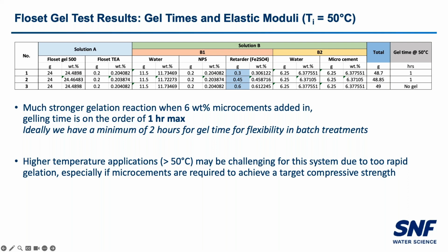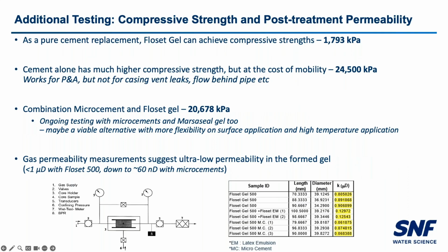Next slide, please. This is showing some compressive strength data that we've done through a third party and post-treatment permeability. So you can see Floset by itself, only about 1800 kPa for compressive strength. Cement by itself might be in that 24 MPa territory. From the initial testing we've done with microcement and Floset gels, we can increase that strength on the order to more of what we see with cements, with having that additional flexibility to place from a surface application.